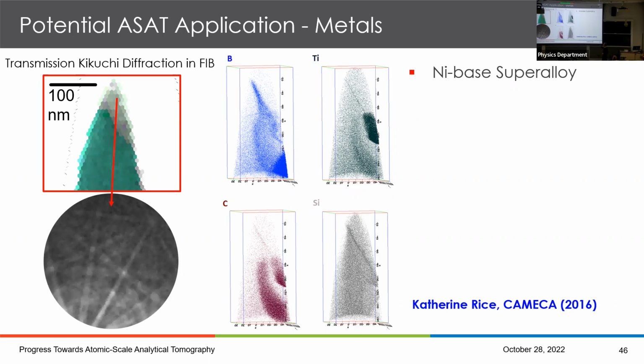They're actually trying to find a grain boundary for the atom probe analysis, and you actually can get diffraction patterns. In this case, pixelated as shown here. And so there's a Kikuchi pattern obtained from, say, one of those spots, and this directly corresponds to this. So in this case, we do know that it is indeed a grain boundary. She has the information that shows what the relative orientation relationship is and other things. So it is a quite high quality result. And my point is that if you're ever doing this kind of work, you really ought to be prepared to back up that that is indeed a grain boundary by some other hard evidence.